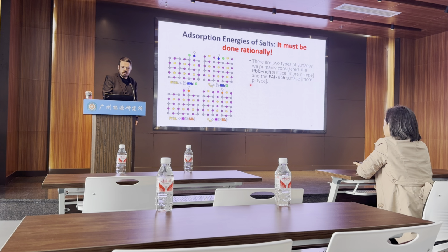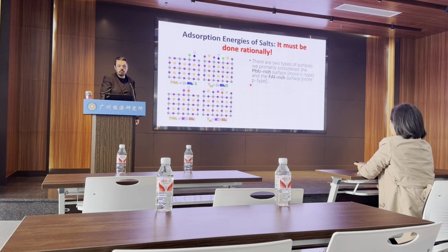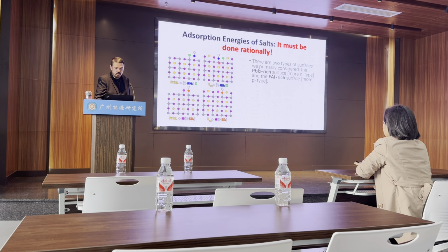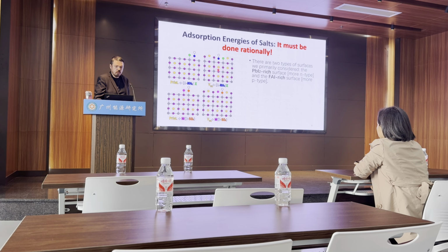So adsorption energies of salts. In literature, this is actually a painful topic because it must be done rationally. So there are 2 types of surfaces generally considered. We're considering the 100 surface because in XRD it is the most well-represented surface type by far. So we get the PbI2-rich surface, which is more N-type, and the formamidinium iodide-rich surface, which is more P-type. And to the left here, you can see the 2 types. So this is PbI2-rich, and this is formamidinium iodide-rich. So you can see this is basically a bare surface, whereas this kind of mixes into the surface. So quite different, actually. And you can see that the sulfonates can just do the same but in reverse. So also interesting.